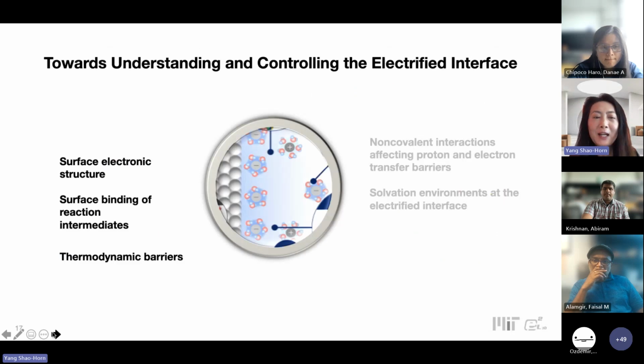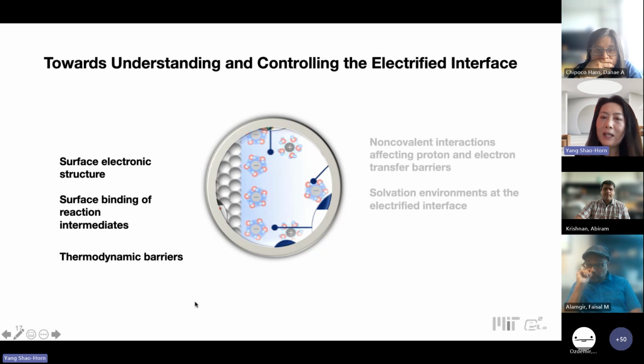We utilize two different approaches. One is through tuning of surface electronic structure to change covalent interactions, for example, adsorption of oxygen or hydrogen on the surface, which changes the binding of surface intermediates and influences the thermodynamic barrier. Through the BEP relationship, or the linear free energy relationship, we can correlate the thermodynamic barrier to the kinetic barrier. Lowering the thermodynamic barrier correspondingly lowers the kinetic barrier, through which we can develop electronic structure-based descriptors to tune catalytic activity.